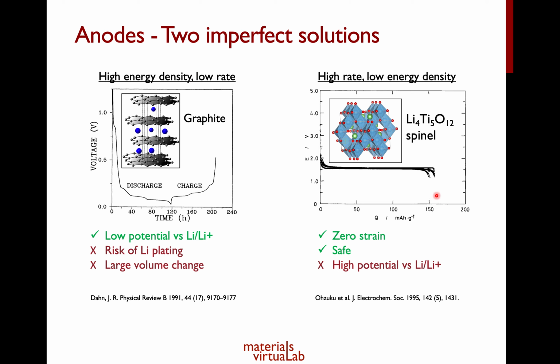Now, there is an alternative to graphite, and this material was also discovered in the 1990s. That is the lithium titanate spinel. While not as dominant as graphite, it is used in commercial applications in very high rate applications. The reason why the lithium titanate spinel is a good anode material is because it is what is known as a zero strain material. When you cycle the lithium titanate spinel, there's negligible volume change, and you can also cycle it at extremely high rates.